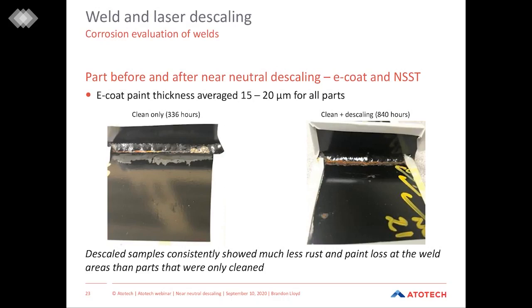And you can see from the clean only part that we have some pretty significant paint loss along the weld area. And for the part with cleaning and descaling with Uniprep AC, we can start to see some corrosion at 840 hours, which is to be expected. But we see that there's significantly less paint loss, showing that the implementation of the descaler is offering a significant improvement versus the clean-only application. So these descaled samples consistently showed much less rust and paint loss at the weld areas than parts that were only cleaned.